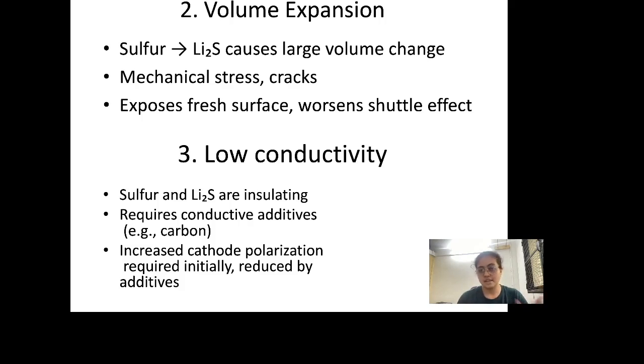But the materials way is that you probably put in additives, conductive additives, and an example of that, as I've discussed in my term paper and as I found in literature, is to add a conductive carbon matrix, which would not only act as a conductive framework, but also, as I discussed before, act as a supportive mechanical framework. So it facilitates conduction of electrons through the cathode, which is going to help with this low conductivity problem of the electrode.